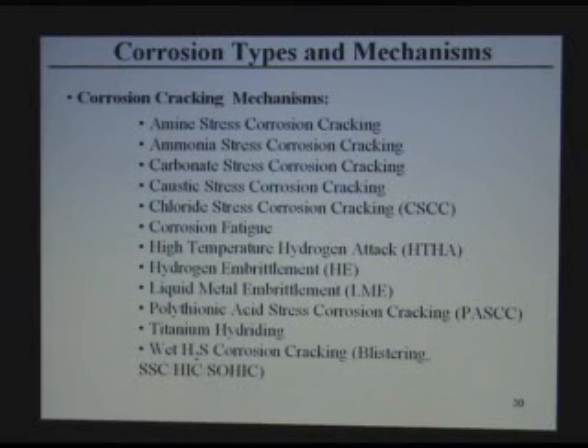So there are operational procedures that you have to outgas before you cool down, or cool down slowly at high temperatures, so you get rid of the hydrogen from the metal. Liquid metal embrittlement: we try to avoid use of galvanized material next to hot surfaces, because of molten zinc, because zinc is a very low melting material.